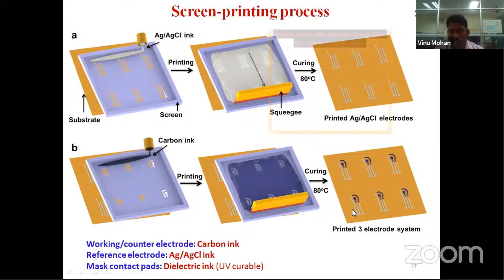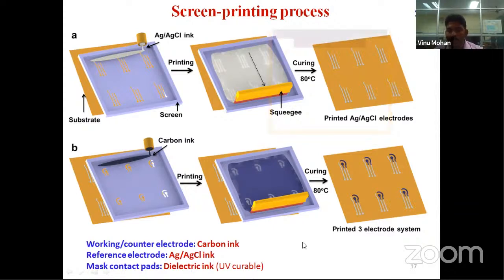The two different stencils we have to use: one for printing Ag/AgCl ink, so all the contacts will be printed initially. Then we have to print the working and counter electrode. For that purpose, we can use carbon ink. So finally, we will get an ideal 3-electrode system. And one more step, we have to define the area of the electrode. For all electrochemical sensing applications, we have to fix the area of the working electrode. So for that purpose, on top of this electrode, we have to print some dielectric ink. Mostly they are cured by UV; just exposed to UV light, it will immediately start the polymerization. Less than 5 seconds is sufficient for curing this insulator ink.